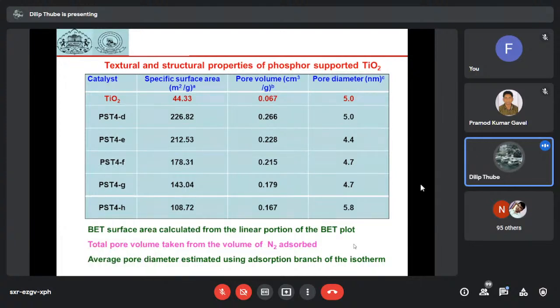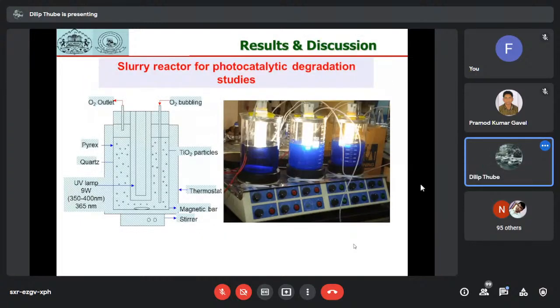Average pore diameter of these materials is estimated using the adsorption branch of the isotherm, and the average diameter is in the range of say 4.4 to 5.8 nanometers for this material. And finally, the photocatalytic degradation experiment has been carried out by using a photocatalytic reactor. This left-hand side picture shows the design of the reactor. There is an arrangement for the lamp, and a quartz container or cell is used. There is an arrangement for the oxygen inlet as well as outlet, and a magnetic stirrer has been placed.